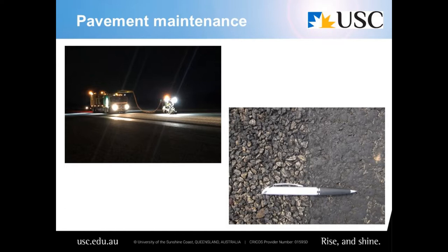You've got very flushed seal on the right-hand side of that picture, and the surface almost completely free of excess bitumen on the left-hand side. And that's a photo of a surface that was actually having the flushed bitumen removed the night before. So it's an immediate effect. And we actually tested the friction on that before and after, and the friction went from very marginal to through the roof, more than you could ever have hoped or wanted in terms of friction. So very effective, but also expensive.